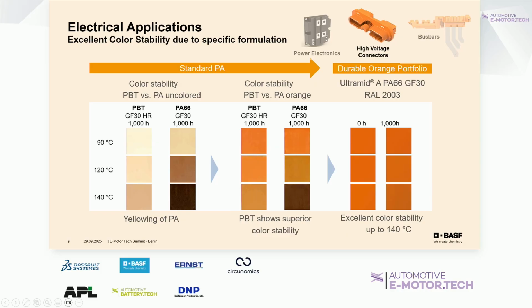You see here a typical aging behavior. If you take a PA66 with 30% glass fiber reinforcement, 1,000 hours, and age it, for example, at 90 degrees, you see the uncolored product still keeps its color. If you increase the temperature, you have this kind of brown effect, so it's getting brown over aging time. And this is something you don't want to have with your high voltage connectors, because in case of an accident, you sure want to see that it is high voltage in the car and not any low voltage grid.